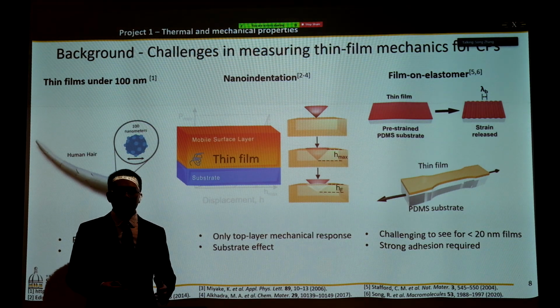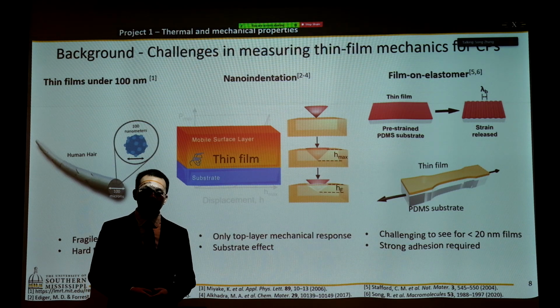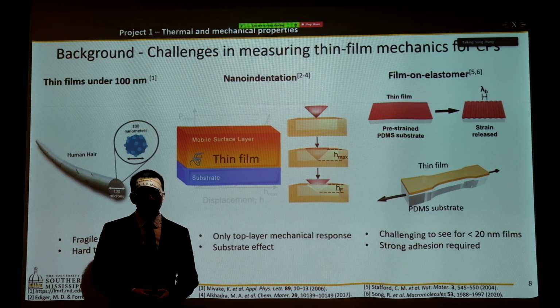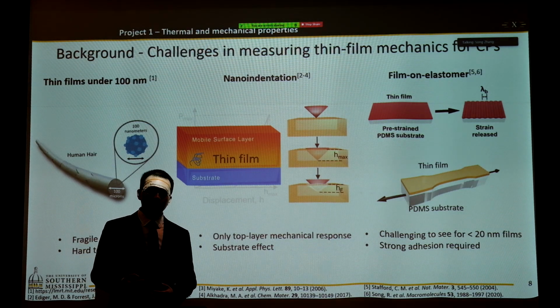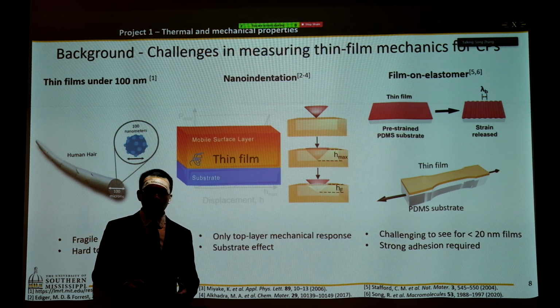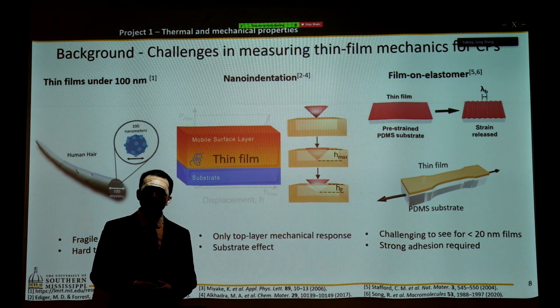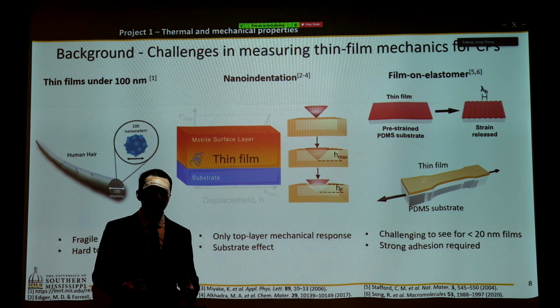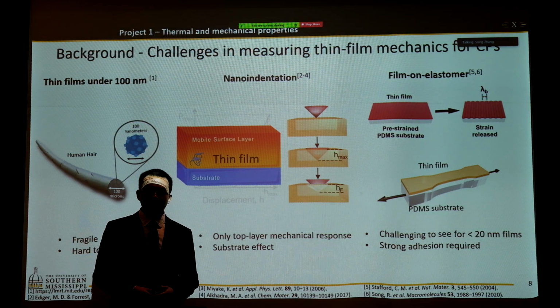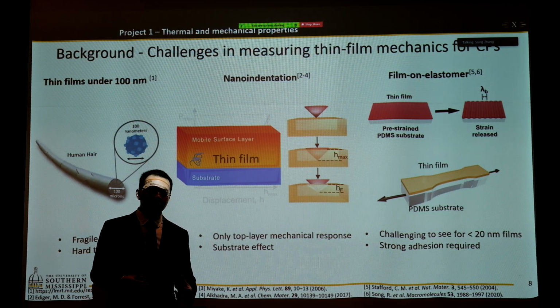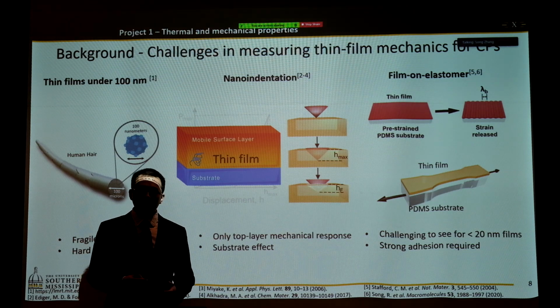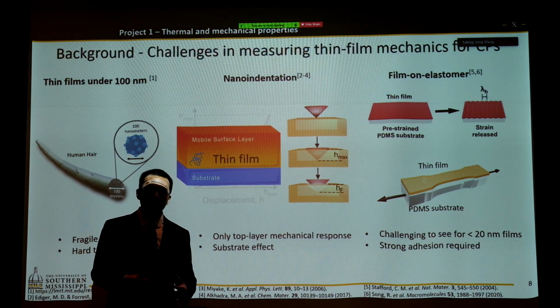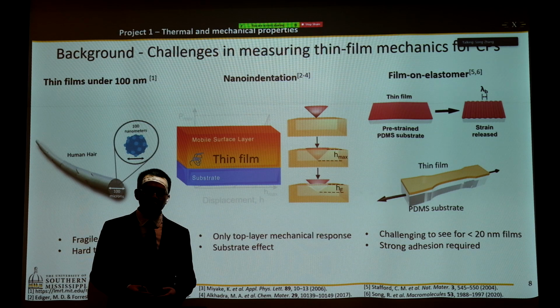So what if we want to measure the fracture strain? You simply use an optical microscope to see at which percentage of strain you get crack formation. However, again, this technique is very hard to apply to ultra-thin viscoelastic polymers because the wrinkling is very hard to observe, and the cracking is hard to observe as well,